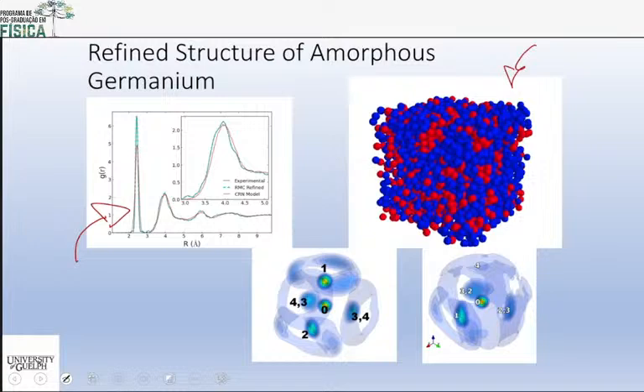Now, we spent a lot of time thinking about this, and we said to ourselves, what are you going to say about this model? And how can we say, now we anneal it and we also fit the data? How are we going to figure out what happened between the unannealed and the annealed, the one that was not heated and the heated sample? The patterns change, the model moves a little bit, but how are we going to describe what's happening in this small structure change? It's just a box of 100,000 dots, right?